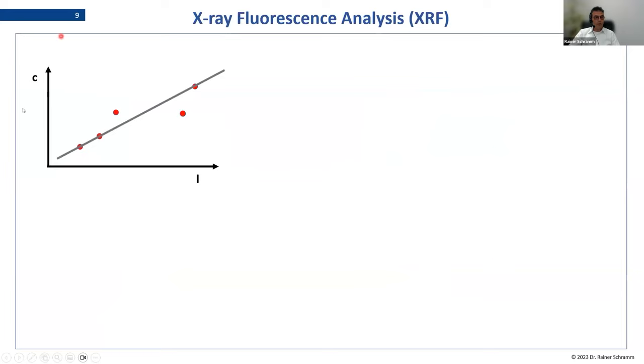So this means in our calibration, we will have points where there is no matrix effects, and so they are exactly on the line. And then we will have points where we have an absorption, so the intensity is too low, and others are excited, so the intensity is too high. And we need now a correction to get these points on the line. That is the whole idea of matrix correction in XRF.